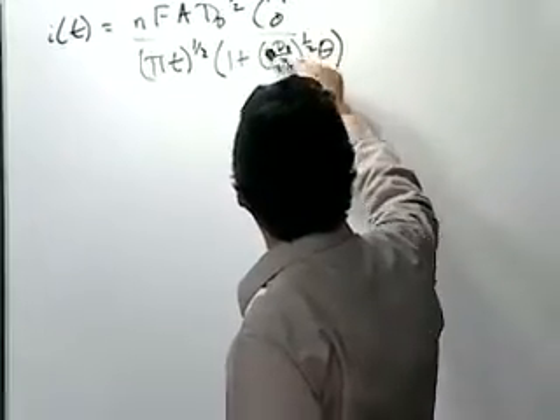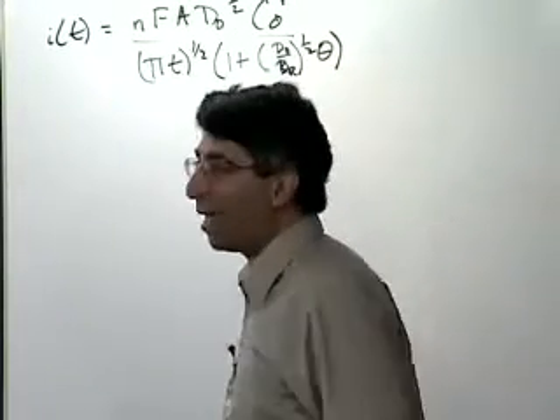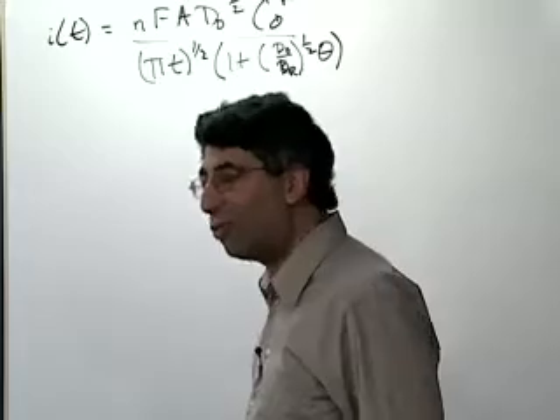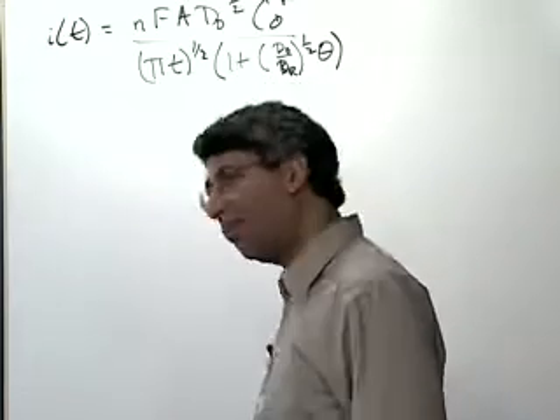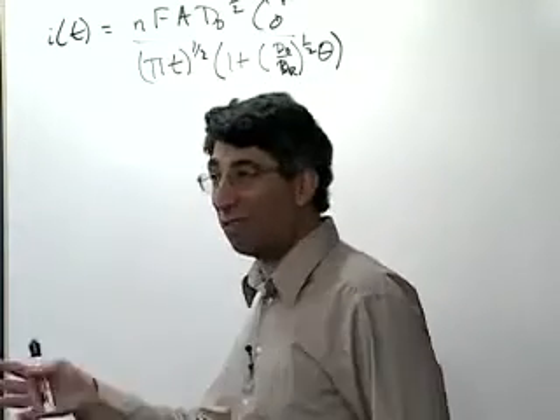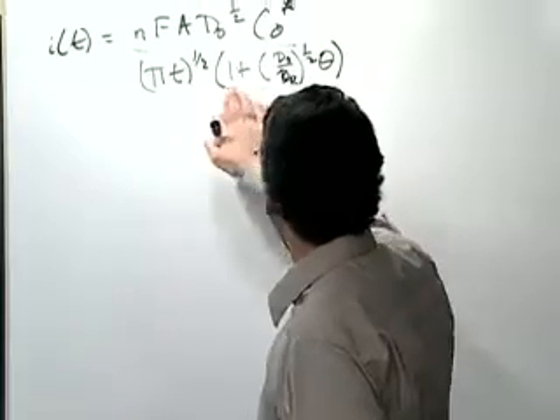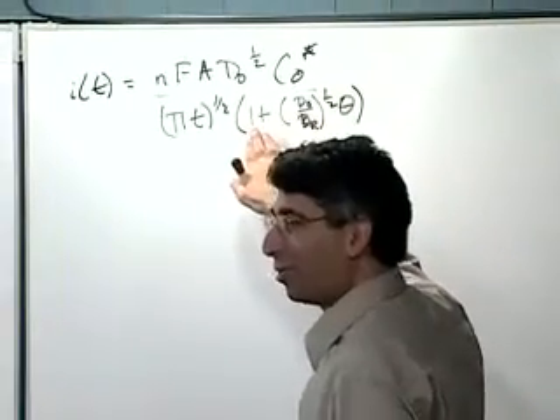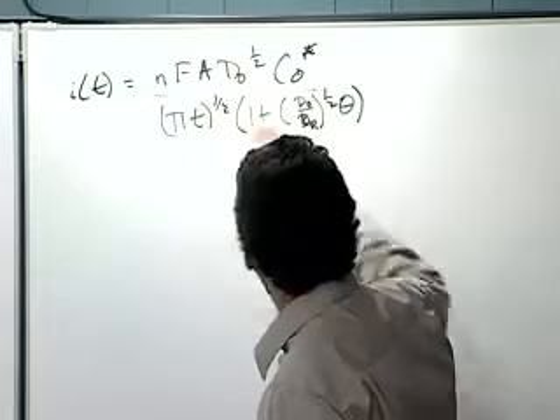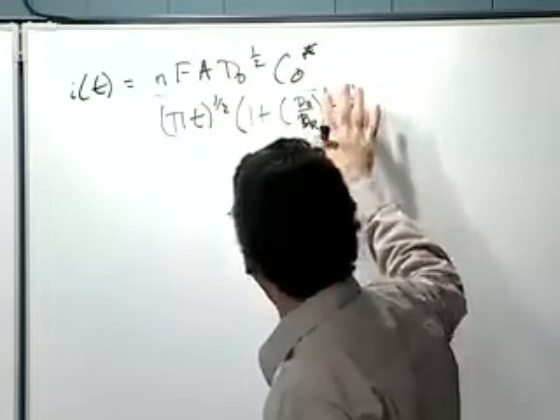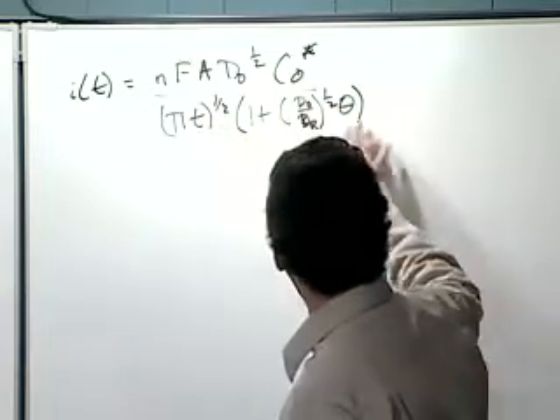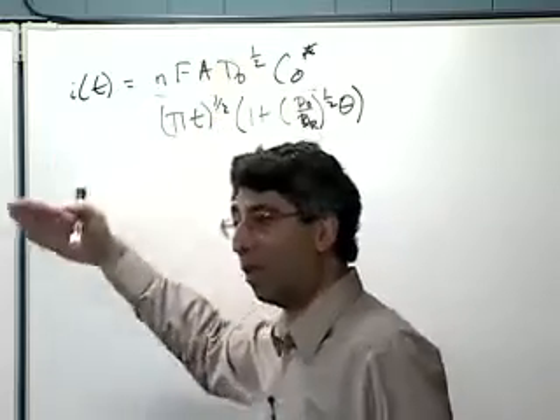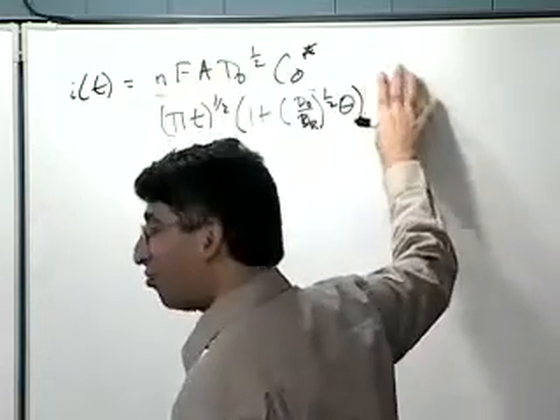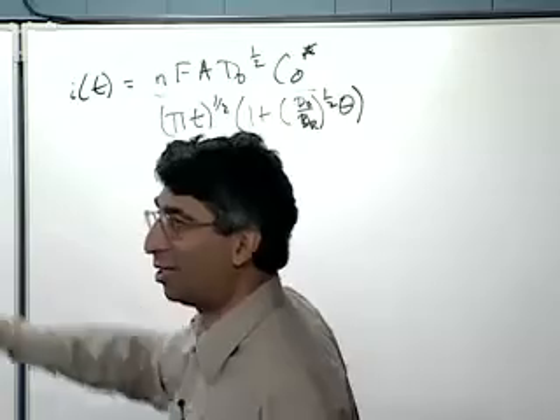And I'll use my standard assumption that the diffusion coefficient for the oxidized species and the diffusion coefficient for the reduced species are about the same number. So this is about 1. So I'm adding a number on here to 1. And so this term down here is always larger than for the large potential step, and therefore the current is always smaller. But you'll notice that this functional form of this equation is identical to the Cottrell equation.